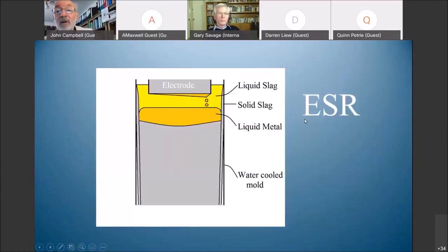And this contrasts with the much lower cost material, electroslag refined material, which is frankly pretty good. Even this isn't as good as it could be because lumps of the electrode fall off, because the electrode is very often top poured. I don't care that it's poured in vacuum. We still create bifilms in vacuum, so this thing has great cracks through it. And so every now and again, a part will fall off into the melt, give a massive defect.